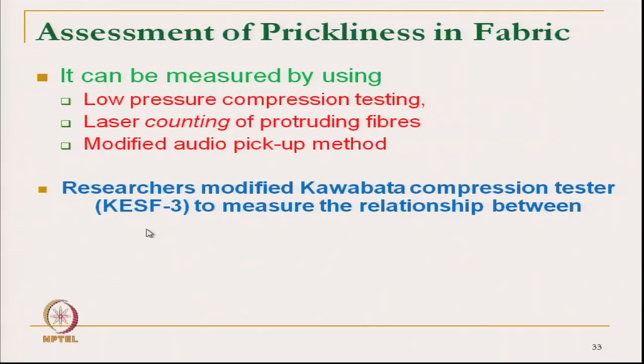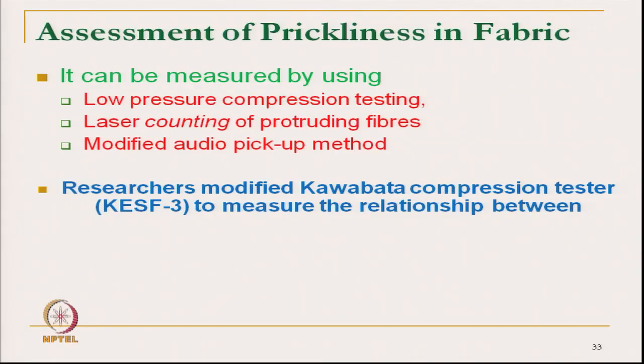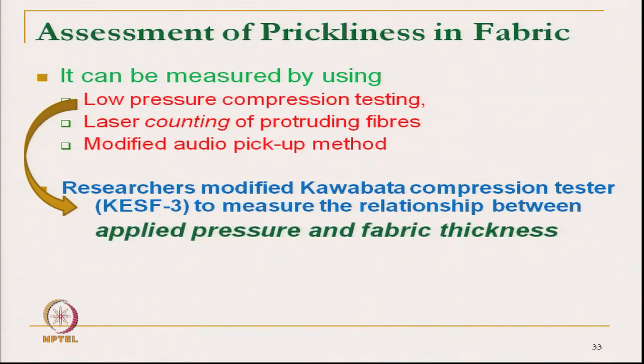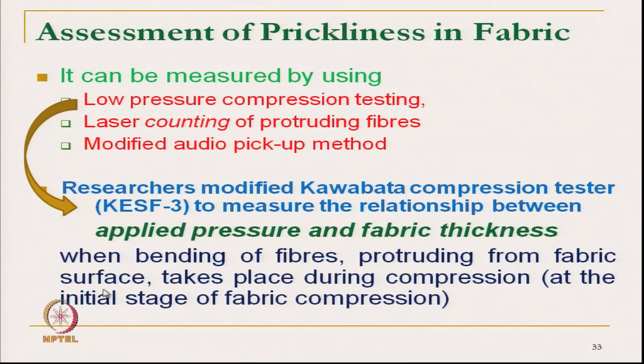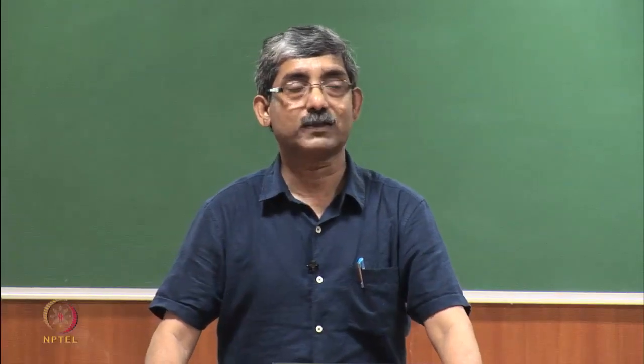If we modify the Kawabata system, like the KESF-3 compression system, which gives low stress/low pressure compression testing, data at low pressure gives the prickliness sensation indirectly. The relationship between applied pressure and fabric thickness can be measured — when bending of fibres protruding from the surface takes place during compression, we can get the idea of hairiness or prickliness.